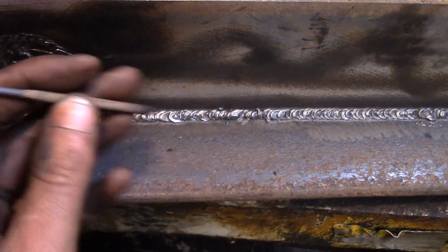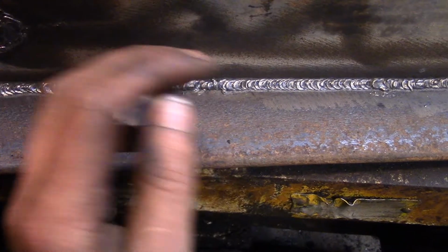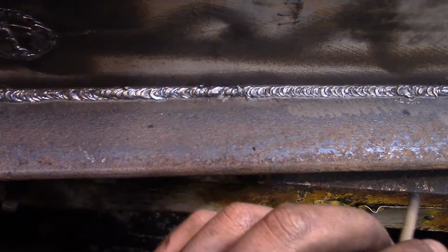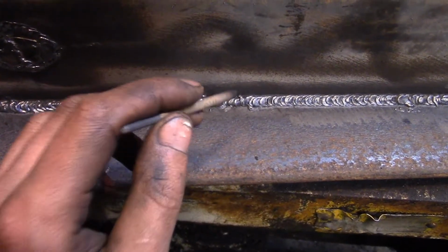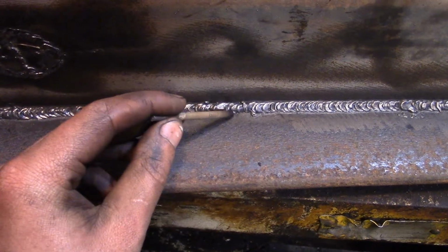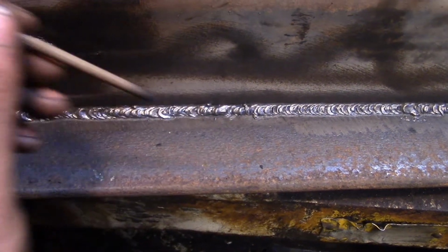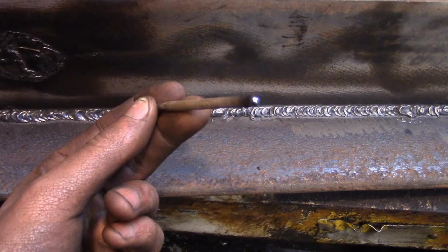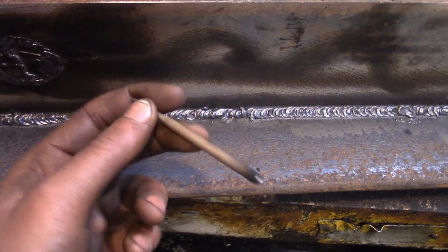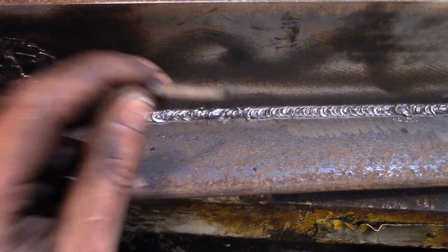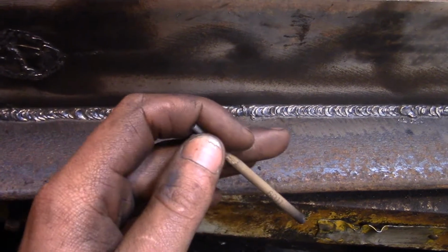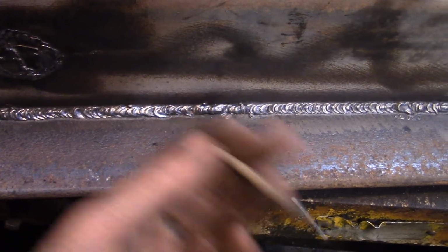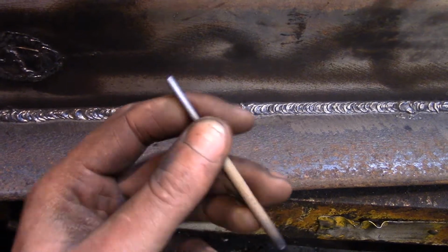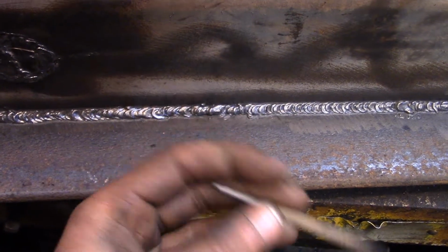But, yeah, like I said, nice smooth bead, runs real nice, thick coating of slag that sometimes gets in the way, because if you're welding over a gap, that slag will fill in the gap before the weld metal does, the filler metal. And you think you've welded the piece together, but when you chip the slag away between the two pieces, it falls apart because the slag was actually holding it together, not the filler metal.